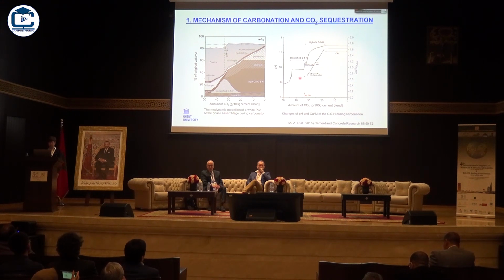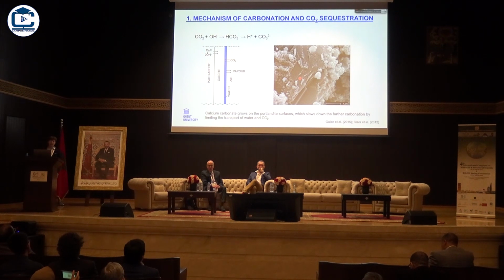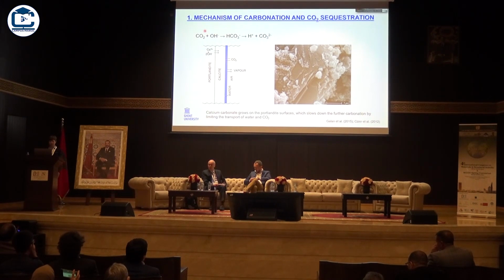So this is the thermodynamic model, but what is happening in reality is that not all the portlandite is carbonating before CSH carbonation is starting, because you have the precipitation of calcium carbonate, as you see here, on the portlandite surfaces, and this forms a layer which limits the further diffusion of carbon dioxide towards your portlandite, and also the further diffusion of water, which is needed for dissolution of carbon dioxide and for the whole carbonation reaction to happen.